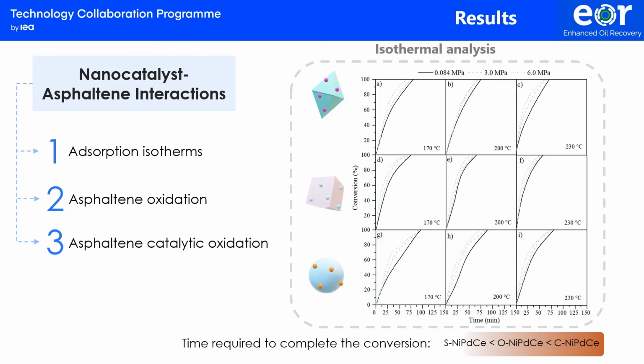On the other hand, the time required to convert the asphaltenes decreases with the presence of nickel and palladium phases. To explain the enhanced activity of the doped materials, two factors are considered. First, the formation and stabilization of highly catalytic active sites of nickel and palladium may depend on the ceria facet's crystallographic orientation, which is improved in the octahedral nanoparticles due to it being endowed by the 111 facets.